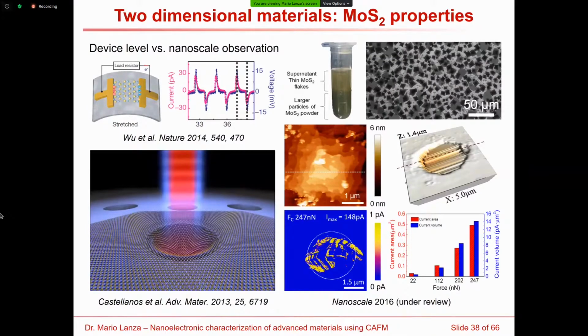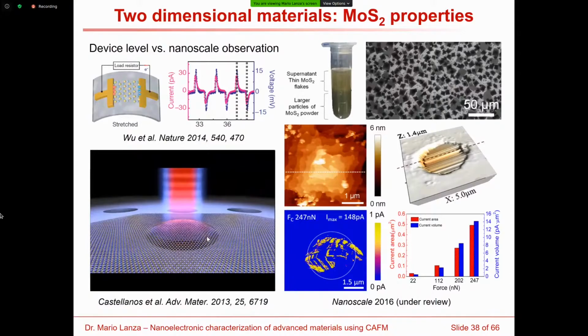by bending this material. This material can be easily bent. As you can see in this video, this is a flexible material. If you put it on a substrate with holes, you can bend it. So our question was how could we measure this at the nanoscale? And we decided to fabricate this material by liquid phase exfoliation. We fabricated one piezoelectric ink of molybdenum disulfide, and we deposited it on a substrate that was patterned with some holes, so that we could go with the tip of the AFM onto the suspended molybdenum disulfide and push with the tip, and at the same time measure the electrical current that was being produced.